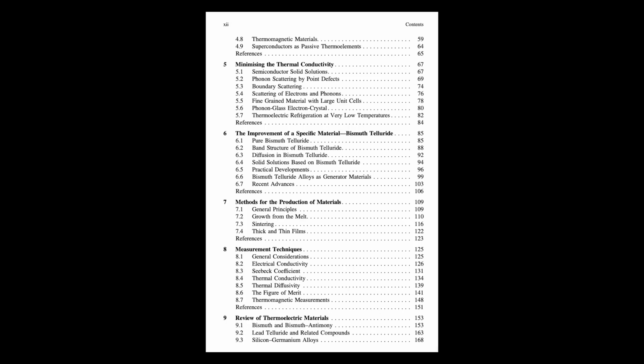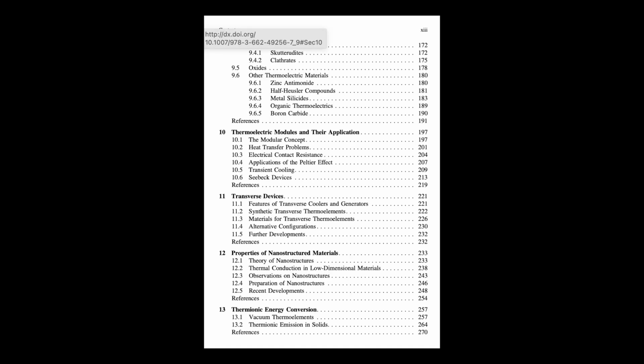And superlattices. How do those layered structures affect heat flow? Superlattices, periodic stacks of alternating thin layers, like Bi-Te. Again, the interfaces between layers are key. They scatter phonons, reducing thermal conductivity compared to bulk. How much depends on layer thickness, the period, and interface quality, roughness. Disorder within the layers might also play a role.